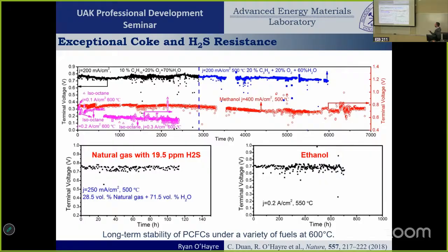You can kind of see the performance starts to drop. This is the voltage. We're drawing a constant amount of current from the fuel cell, and we're just watching how the voltage drops over time. But yeah, we were able to get a couple thousand hours out of isooctane. Here we did an experiment where we purposely added sulfur contamination into natural gas, and it didn't really affect it. Sulfur will kill almost any other fuel cell, so that was huge.